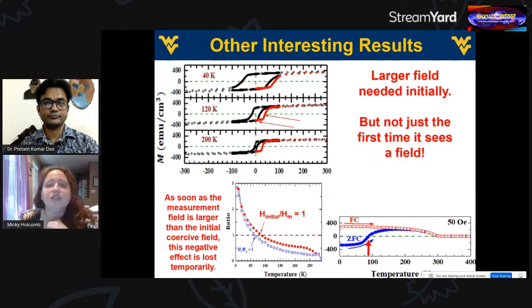Another important note is this isn't just some initial parameter that has to be annealed out of the sample, right? You can't just make this go away after one time. This keeps happening over and over. These 3 measurements are all on the same sample. All we had to do was wait a little bit, and this initial magnetization came back. So it's not something that, once you saturate it with a field, you don't have to worry about anymore.